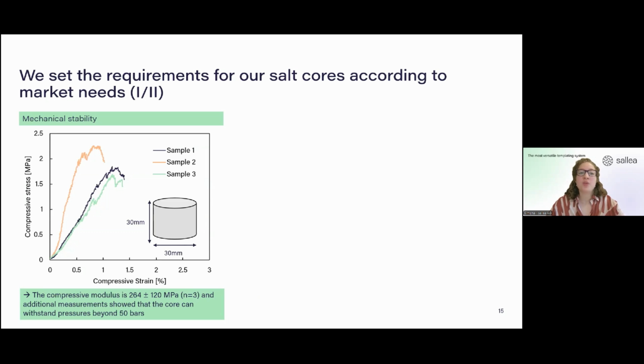Now, the one I want to start with is actually the mechanical stability. Processes to make carbon parts usually require that the salt cores are stable up to several bars, if you're talking about, let's say, standard RTM or autoclaving processes for thermoset materials. So we did conduct some compression tests on our end with our samples. For that, we used cylindrical samples with the same diameter and height. And here on the slide, you just see an example of 3 samples that we have tested recently.